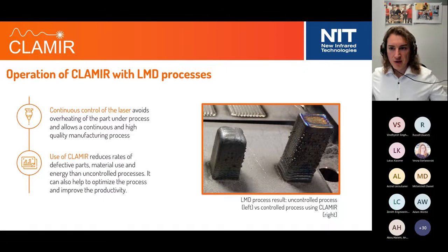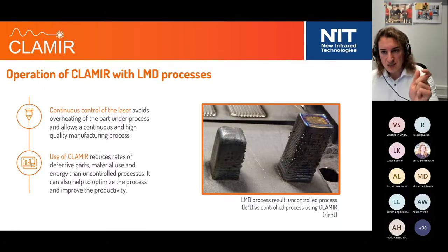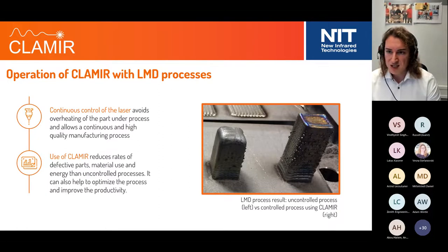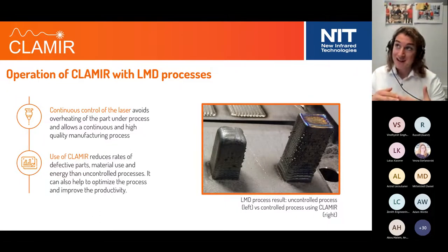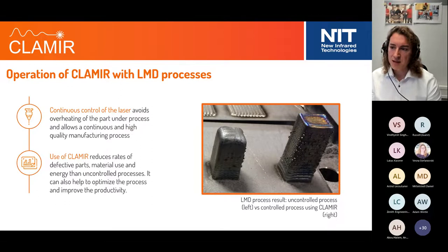If we talk about even larger scale components, when you build components of 1 meter, then the process control, to ensure that the melting bath remains the same and you do not overheat the components, gets more importance. I believe there should be one step further made in that direction in terms of artificial intelligence, in terms of signal correlation between your working head, computer program, and also the movement of your axes, so that you get much better control. Also, the powder is a high factor in how you can differentiate the temperature gradients which might appear, as you always have powder particles interacting with the surface.